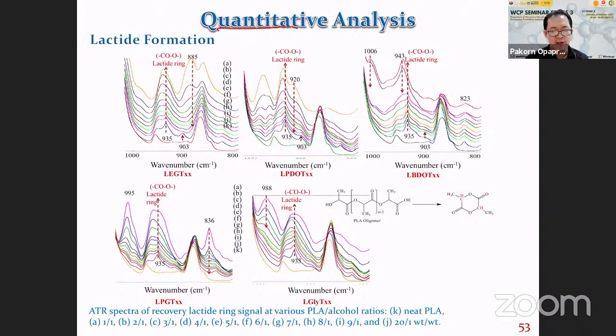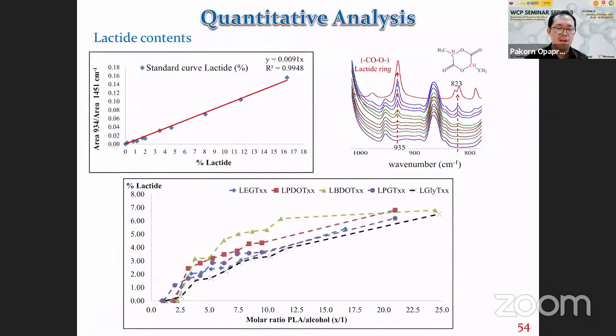This result shows us a formation of lactide from degradation of PLA. We see this peak right here that changes with the condition of our reaction. So if we want to quantitatively determine how much, we can prepare standard sample, and then measure intensity of the characteristic peak, and then make a standard curve. After having standard curve, now we can determine the amount of lactide in our sample. So these are the results.